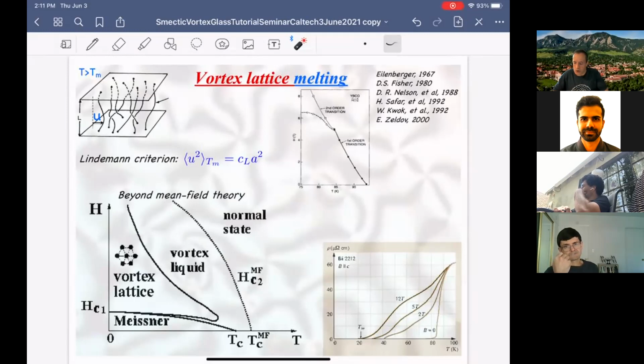So the first thing that happens is, because of the properties of high temperature superconductors, first they're layered. Second, they occur at high temperature. And thirdly, the coherence length is very short. As a result, these vortices that are treated in mean field theory by Abrikosov become dynamical entities of their own. They take on a life of their own. And just like any other constituent, you could have a crystal phase of it, or other phases. You can start talking about phases of this vortex matter. The Abrikosov lattice is just one phase, the solid phase of these flux filaments, of vortex filaments.